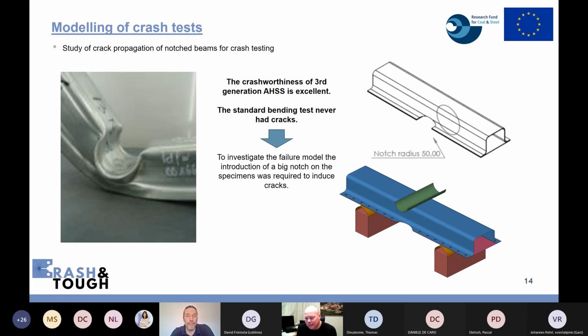Okay. Also, as you saw in a previous presentation, the crashworthiness of this third generation of advanced steel is excellent. And we never found cracks in the bending crash test using the standard specimen. For this reason, in order to investigate the failure simulation model, we introduced these 2 big notches at the middle bottom part of the specimen. With these two notches, we were able to induce cracks and obtain a full material failure in this area.